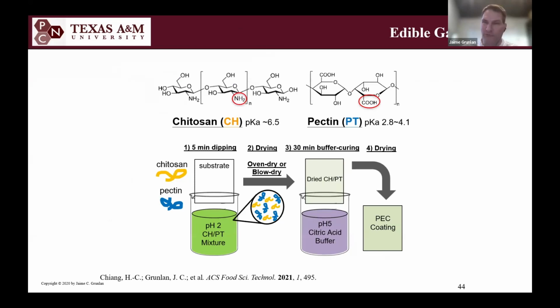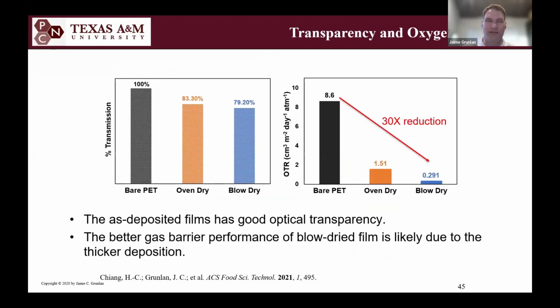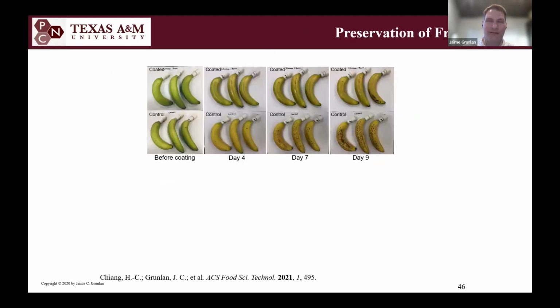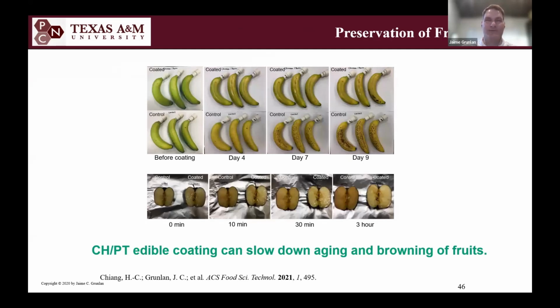You can even make an edible version of what I just told you by using chitosan and pectin instead of PEI and PAA. Exact same kind of concept. And we directly dipped bananas and apples into that polyelectrolyte complex. That was kind of fun, and it slowed the browning and slowed the oxidation. It turns out that dip coating was approximately 700 nanometers thick on both the banana and the apple. Kind of a cute demonstration there.